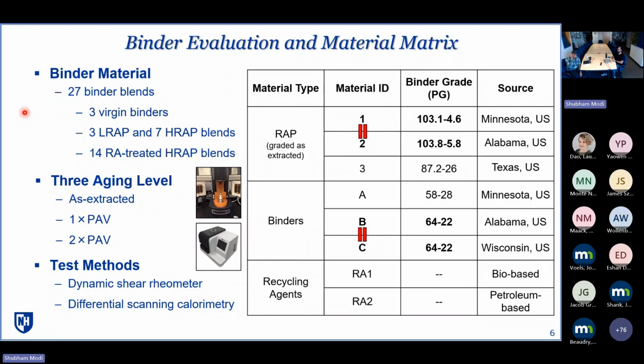Just to make one comment on the blend side: the blends were not primarily made by just blending the binders in the lab. To be consistent with the mixture test results, because we wanted to compare between the binder properties and mixture properties, the test results where you see blend results are materials that were recovered from asphalt mixture. So for example, for a high RAP blend, we would have a lab mixture with high RAP amount, where we would do the mixture testing, and then some of that mixture would be put through extraction and recovery, and that's what would give you the binder, just to eliminate another variable of some differences that you may get when it has not gone through the mixture production.